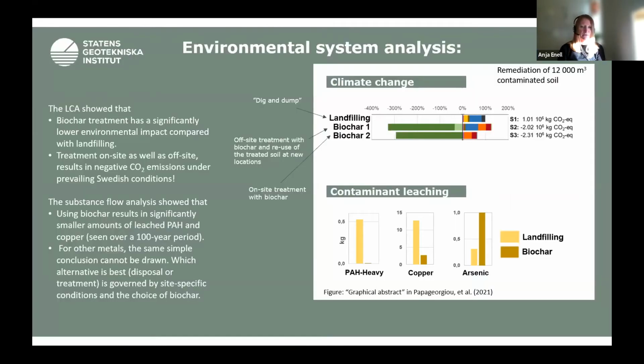I think I have time to give you some results also from our environmental system analysis. So this is what we are looking at here. In this LCA, we compared the alternative to use the dig and dump technique and excavate the soil and put it on the landfill. And this alternative was then compared to off-site and on-site treatment with biochar. And our LCA showed that the biochar treatment has a significantly lower environmental impact compared to traditional landfilling. And treatment both on-site as well as off-site resulted in negative CO2 emissions under prevailing Swedish conditions.